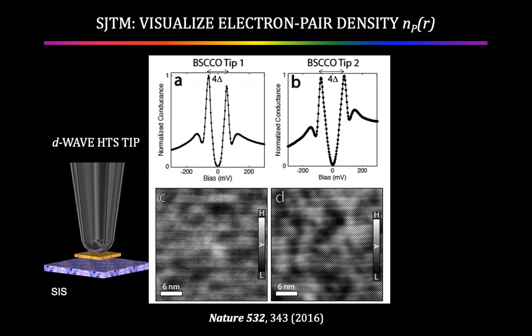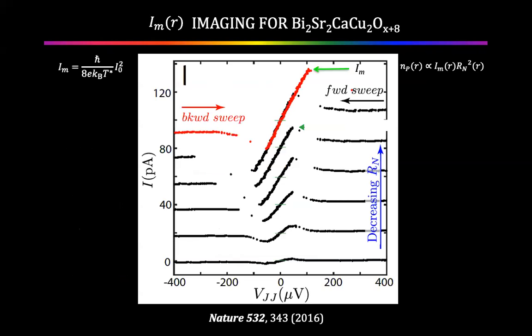And these are different tips. We have a recipe for this, and our colleagues in Brookhaven have a recipe for this, which works in Brookhaven as well. So although this is magic, it isn't black magic. Furthermore, using this scheme, we can retain the atomic resolution. So now we have a D wave, high gap, high TC tip with atomic resolution at millikelvin temperatures.